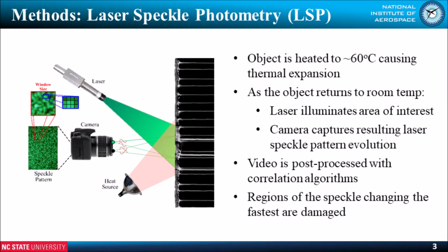First, the object of interest, in our case a composite panel, is heated to about 60 degrees Celsius with a heat lamp. As the temperature increases, the composite expands due to thermal expansion. Next, the heat sources are removed, allowing the object to return to room temperature. Simultaneously, the laser is turned on, and the camera starts shooting video of the region illuminated by the laser.